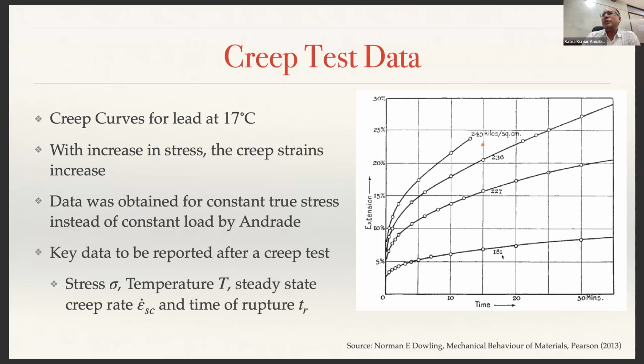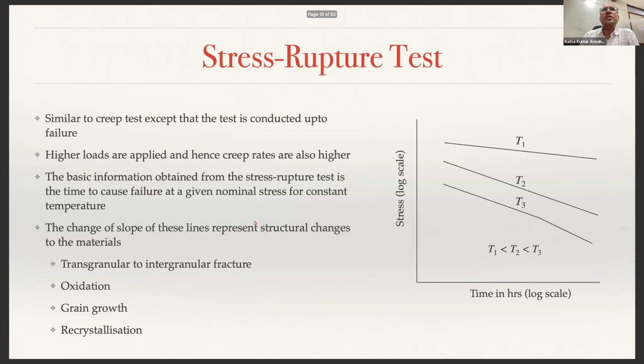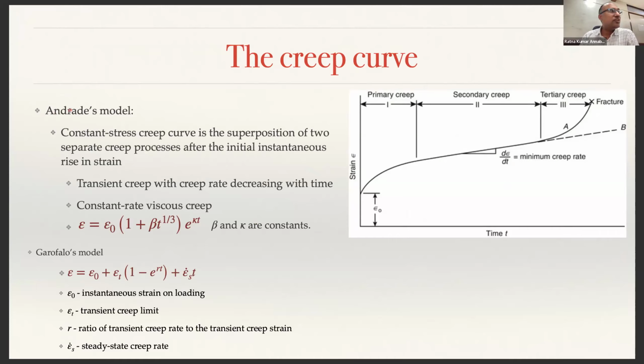So these are data shown for lead. Lead being a very soft material, at 17 degrees Celsius itself, it shows some creep behavior, right? These are all at different stress values, loads are constant, stress values, the strain versus time. So as you can see, with increase in stress, the creep strain also increases, right, for a given time. So this data is obtained for constant true stress instead of constant load by Andrade's formula that we have used, it is obtained by Andrade.